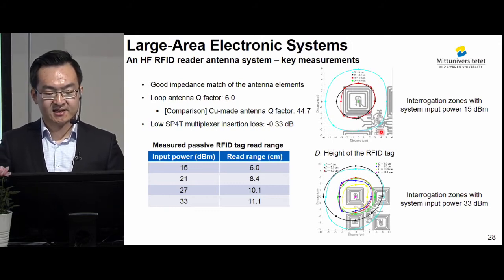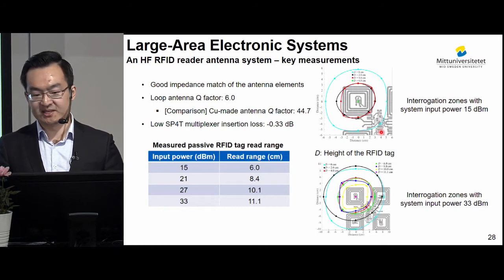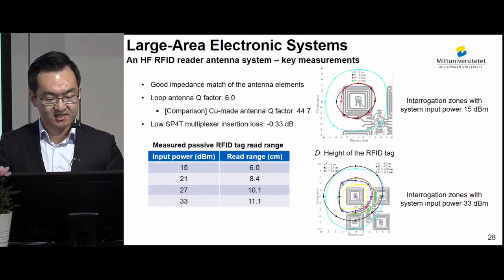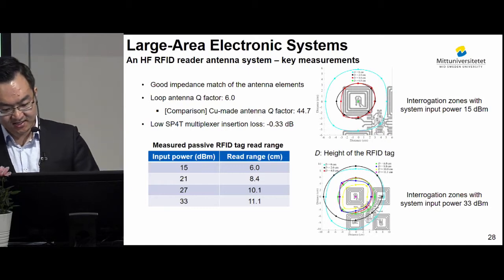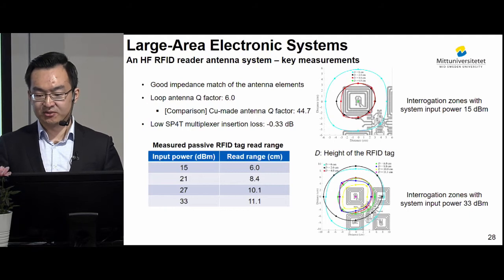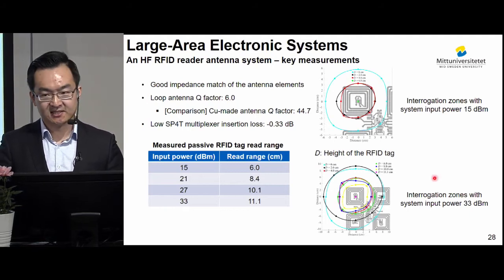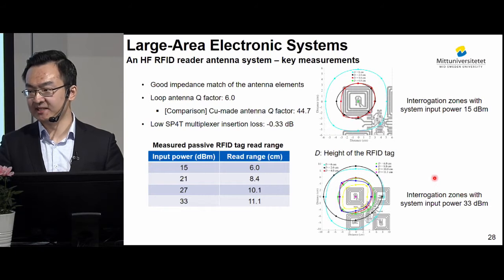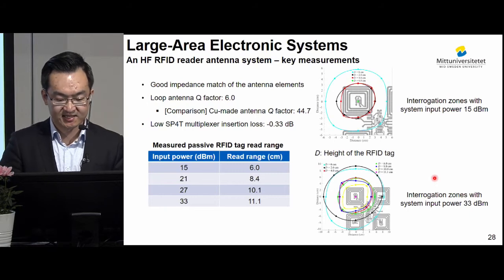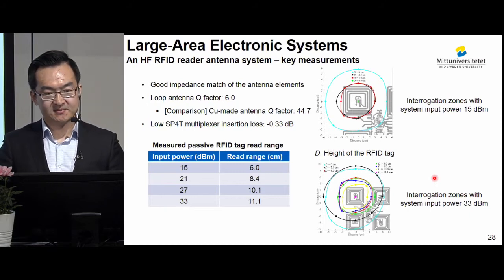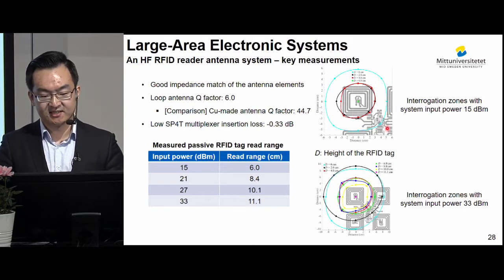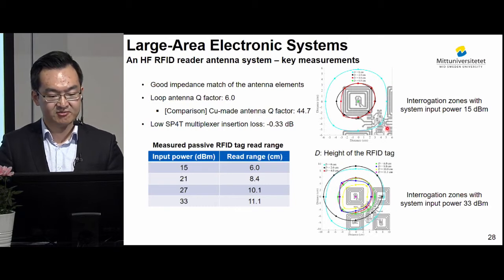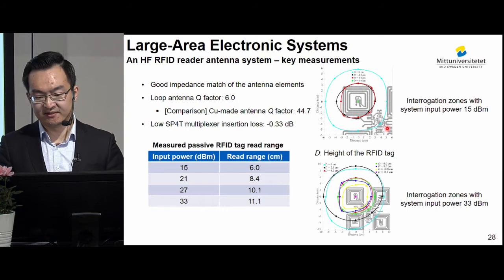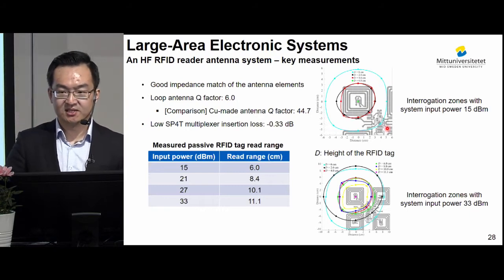And we also measured the RFID tag interrogation zones with different input power, the results of which are presented here. It can be seen that interrogation zones can be controlled by input power and heights. And if we use these 2 parameters wisely, we could avoid RFID interrogation dead zones on top of the antenna system. And it can be seen that we have very confined RFID interrogation zones, which are in the range of a few centimeters. And this is a good feature when it comes to RFID tag positioning.